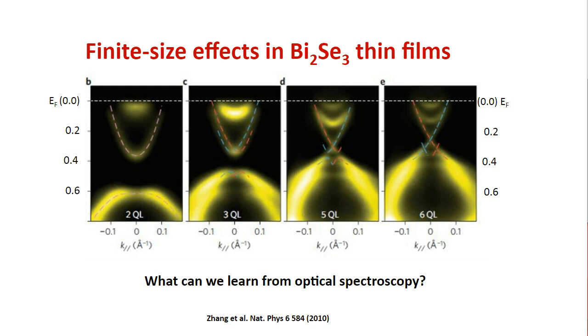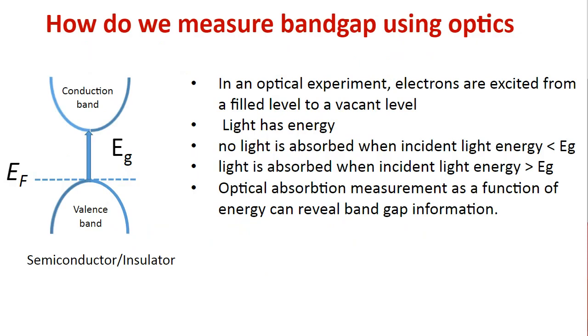So we thought, can we measure this gap change due to the finite size effect in bismuth selenide thin films? How we measure the band gap: no light is absorbed when the energy of our light is less than the band gap. And as soon as we apply a higher energy light, which exceeds the band gap, we see optical transitions, which result in absorption. If properly analyzed, we should be able to extract the band gap information. This is standard information, going back to what we were talking about earlier. So it should be clear at this point.